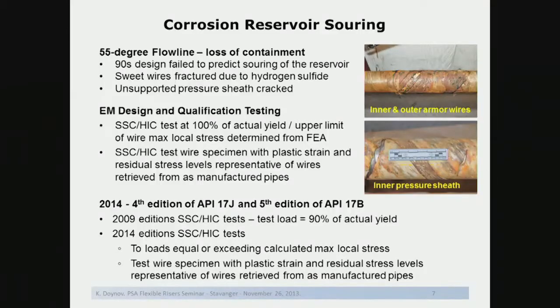And the third example is about corrosion from reservoir souring. We had a 55-degree structure installed back in the mid-90s. It was designed at the time for sweet service. At the time, we failed to predict the reservoir souring. That happened fairly recently. As a result, the sweet wires fractured due to the presence of hydrogen sulfide, and the unsupported pressure sheath consequently cracked. So then we had to replace the entire field from sweet service flexibles to sour service flexibles.